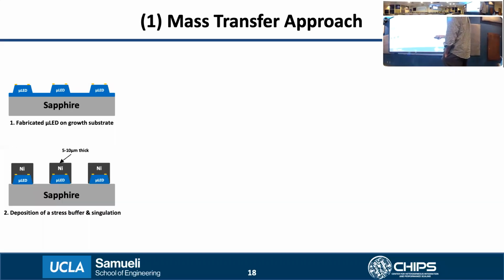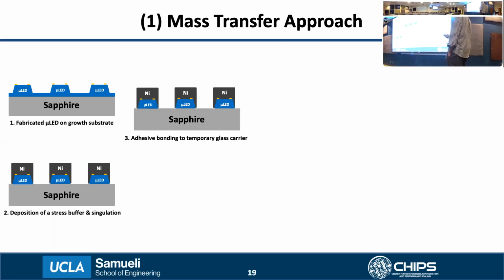In the second step, we deposit or electroplate a 5 to 10 micron thick layer of nickel on top of these devices. The reason for this I'll talk about later. It is to act as a stress buffer during the laser liftoff process for releasing these devices. And we use the same nickel to also dry etch the UGaN between the devices so that they are now completely singulated.